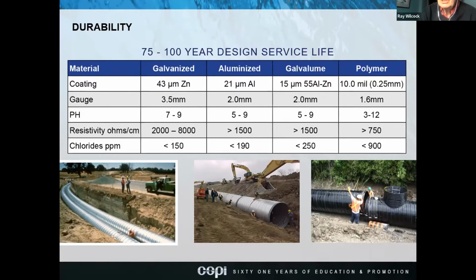The gauge will go down because as you get a stronger coating like a polymer, you don't need a thickness of steel that you would versus say galvanized. So for instance, for galvanized, to get the 75 to 100 year design service life, we need to use a 3.5 millimeter thickness. For aluminized and galvalume, we can use 2, and then for polymer, we can use 1.6.